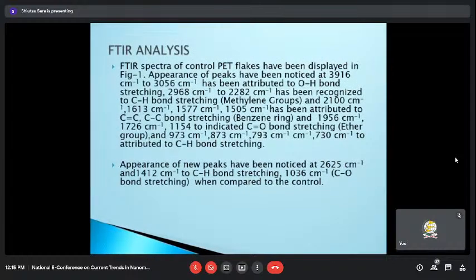And from the FTIR analysis, we have also found the presence of functional groups such as the OH bond, also CH and C double bond O. And we have also noticed the appearance of new peaks corresponding to CH bond stretching and the CO bond.